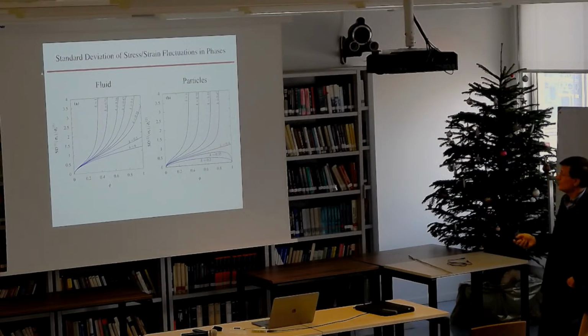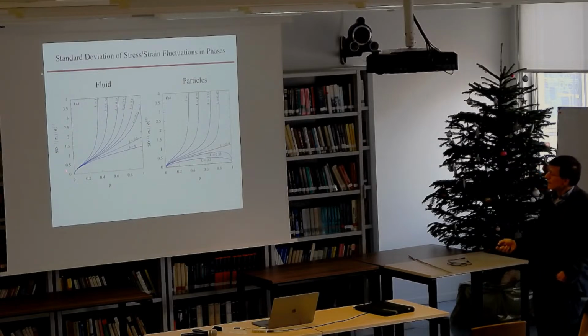So that's something that makes sense and describes the distribution of stresses in the suspension. You can also get information about the standard deviation of the stresses in the two phases. This is the fluid or the matrix, and these are the particles. And this gives us another way to interpret these results.